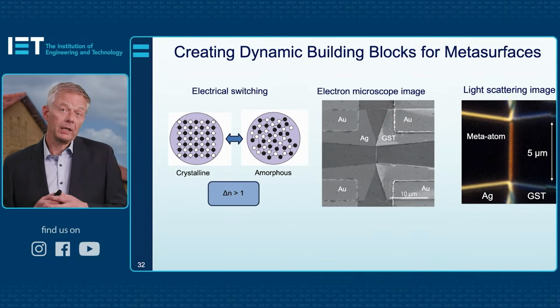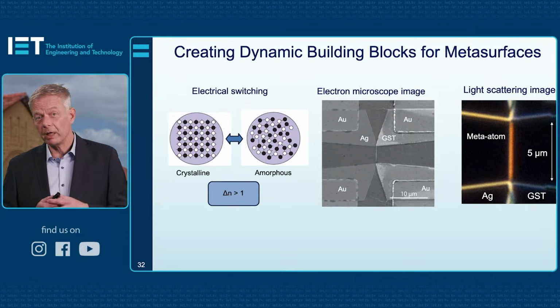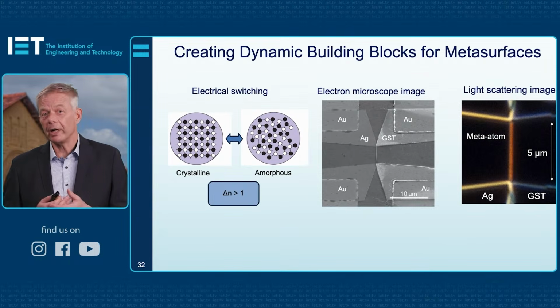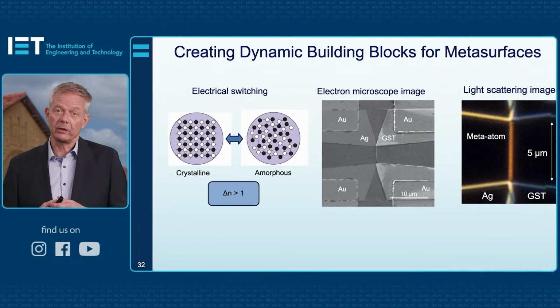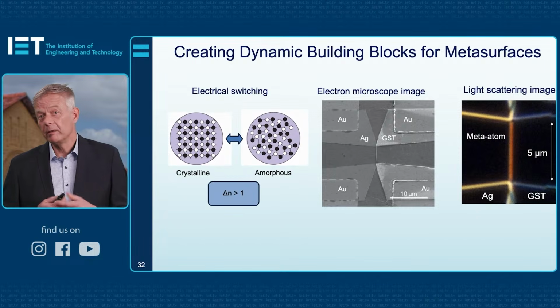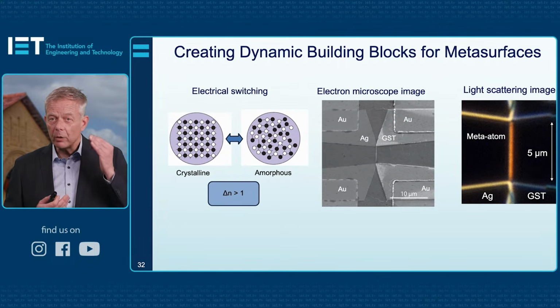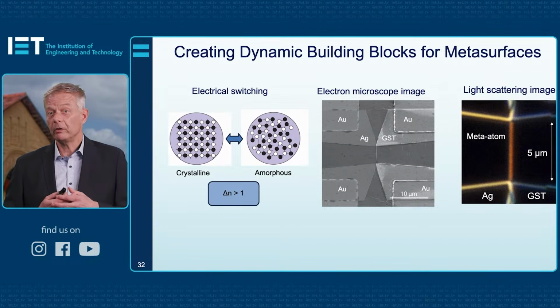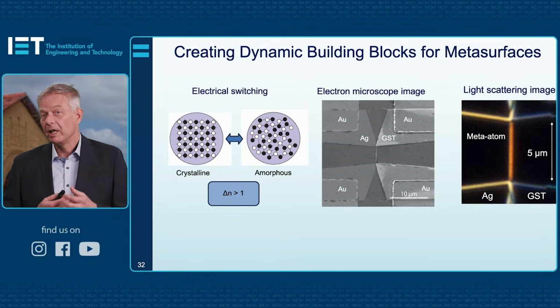In the center you see an electron microscopy image of our device, where we have a little metallic wire and contacts where we can drive electrical current pulses, but then also on top of that wire sits a phase change material wire, GST, that changes the scattering properties through its change of the refractive index. On the right is what you would see in our optical microscope in the dark when we illuminate our wire with white light. It changes its scattering properties as we run these different currents through the metallic wire, pulses of different duration and length, to allow you to tune the scattering of the wire.